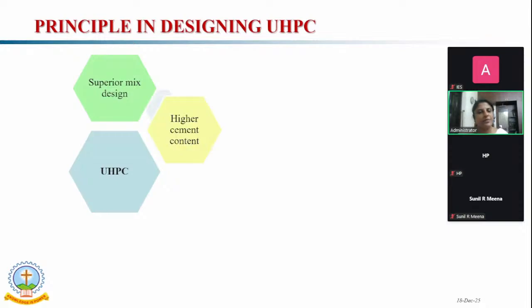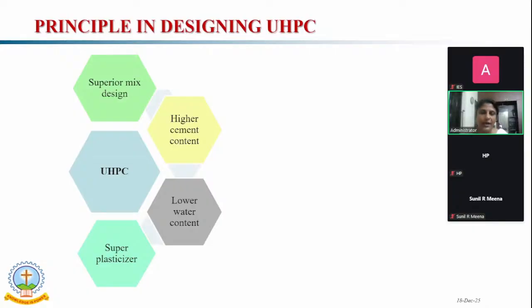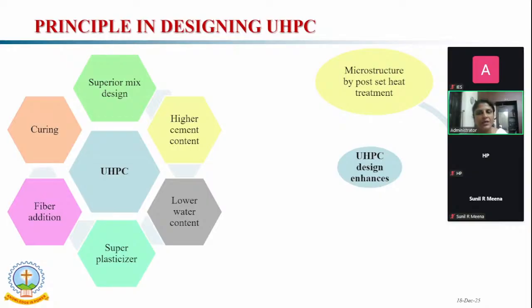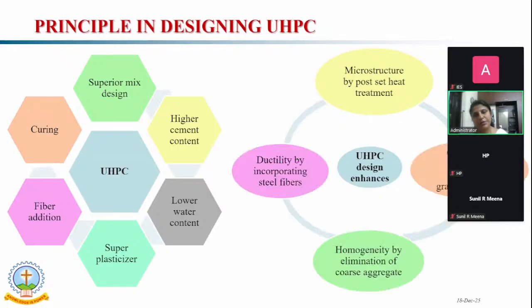UHPC needs superior mix design, high binder or cement content, low water content, a high-end superplasticizer, fiber addition, and the curing method. By considering heat curing, we can enhance the microstructure through that heat treatment. In order to obtain high performance, as I said earlier, we have to consider the maximum particle packing density. That has to be achieved by optimizing the granular mixtures.